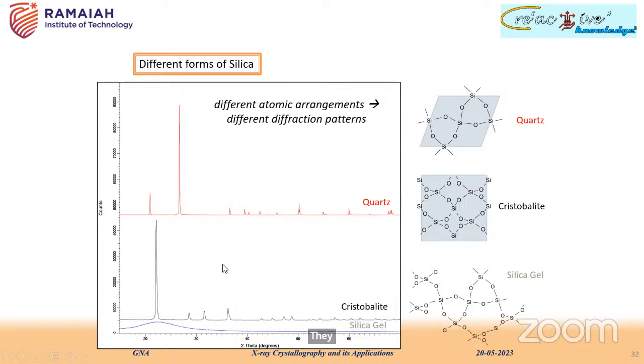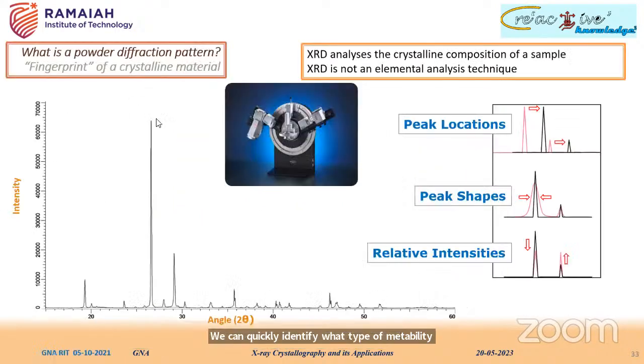By looking at the peak pattern, we can identify the material, because we can match it with the database. In the database, we have standard material structures, and when we match our experimental peaks with the database, we can quickly identify what type of material it is. This is called phase identification. Therefore, the powder diffraction pattern is a fingerprint of a crystalline material.